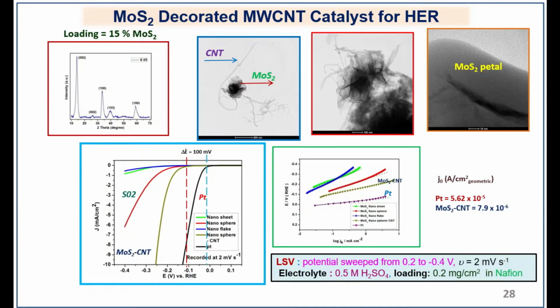We took 15% loading of MoS2 by synthesis itself, where we put together the multi-wall CNT and decorated the material over the top, and then we grew it. We have characterized them by XRD, FESEM and HRTEM. The material grown over CNT is stable, and it has a flower shape.